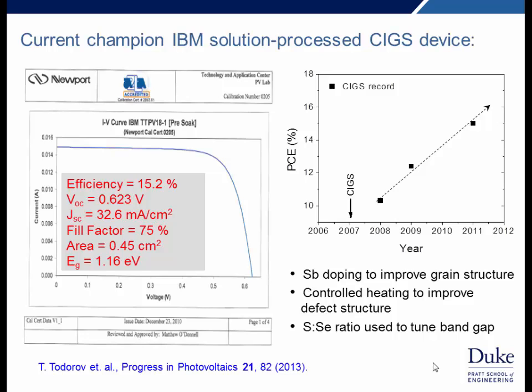And so using approaches like this, the antimony doping, controlled heating, also controlling the sulfur to selenium ratio, we've been able to go from 10% devices back in 2008 up to above 15% devices more recently. This shows one of our record devices that we made. And so we were very happy with these results, but decided that it would be a good idea to try this approach with other materials.